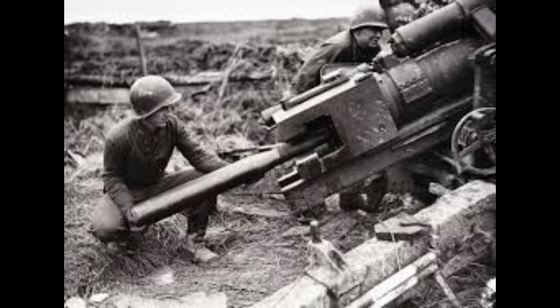But Buckley had seen something in the shipyards of Camden, New Jersey, that contradicted everything the experts believed. He had watched armor plates crack and spall under testing, had examined the failure points, had traced the fractures through continuous weld beads that were supposed to provide strength. He had developed a theory that the experts considered heresy, that continuous welds in thick armor plate created internal stresses that actually weakened the assembly under high-velocity impact.